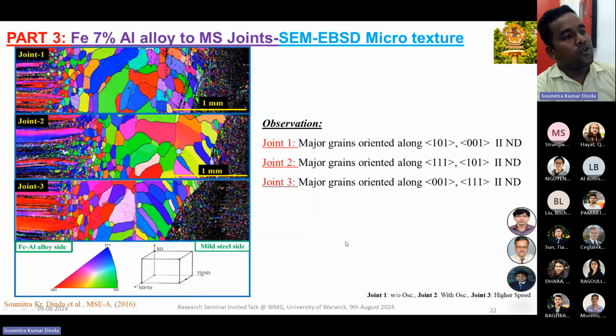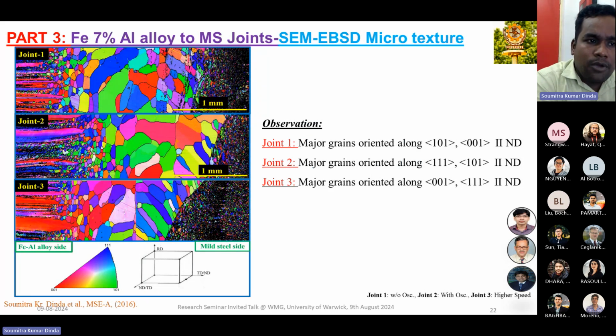And then we go for the textural study using EBSD. That EBSD texture is called the micro texture, because the electron beam can penetrate up to 10 to 20 micron of depth from the surface, and this textural study covers that 10 to 20 micron. So this is the FeAl side, and this is the mild steel. Okay, and this is the last one.